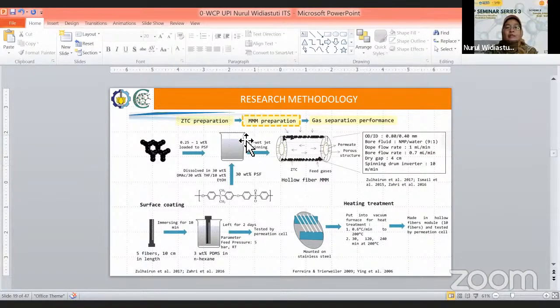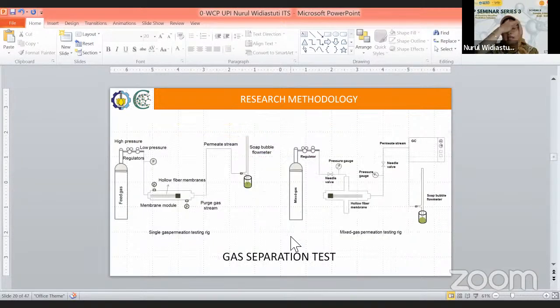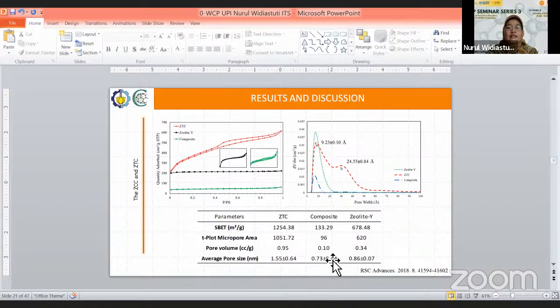In general, we prepare the polymer solutions, and we use the module called hollow fiber. We use the hollow fiber membranes with certain conditions for the preparation, and then we follow with the surface coating and heating treatment. After that, the membranes were tested using gas separation tests for single gas and also for mixed gas tests.